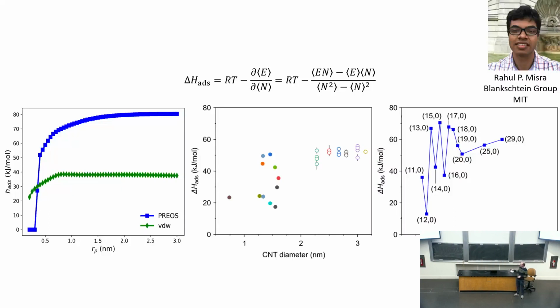Interestingly enough, from analyzing simulations we did based on this statistical physics expression here, we can also reproduce these very discontinuous changes here as a function of diameter in this space. And afterwards, it tends to level off towards a bulk or flat graphene-like behavior. Continuum models themselves, so these are equation of state models that don't take into account molecular packing or whatever, don't show any of these discontinuous trends here. So we believe this is a unique effect that we only see in very small confinement.